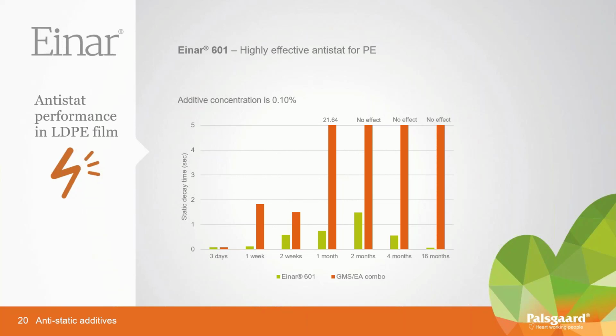Einar 601 offers excellent performance in a very broad range of PE applications. Results shown are for a 30 micron blown low density polyethylene film. And our Einar 601 is shown here to really outperform the ethoxylated amine and GMS combination, both short term and long term.